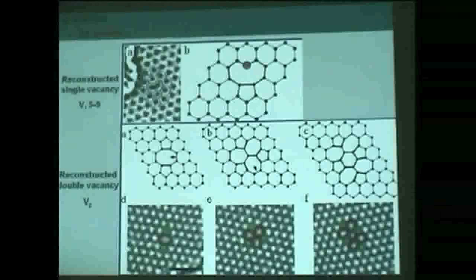So you remove one atom here. What happens, from simulations and from characterization by TEM, is that there will be some reconstruction locally because this is not stable enough. So instead of having these 3 rings missing one atom, the rings will rearrange, reconstruct, and form this pentagon ring. This final state is more stable, and at the end, instead of just one atom missing here and 3 broken rings, you've got the formation of this pentagonal ring and this big ring made of 9 atoms, 1 pentagon and 1 nonagon. This is one type of reconstructed single vacancy defect, called 5-9.